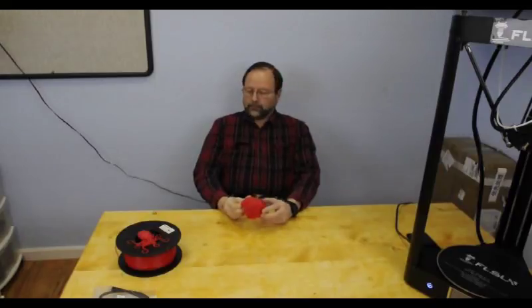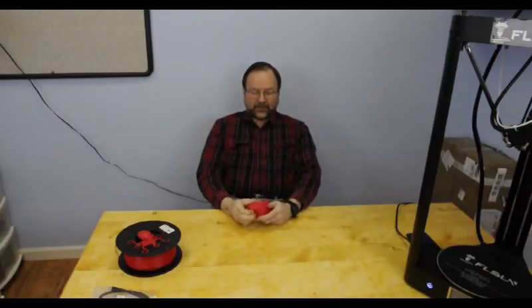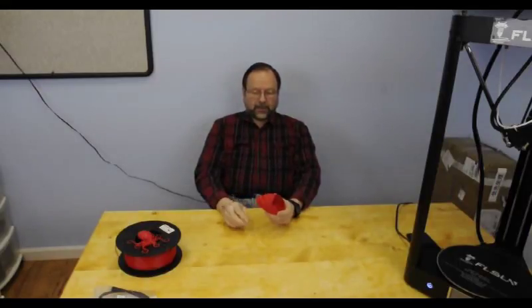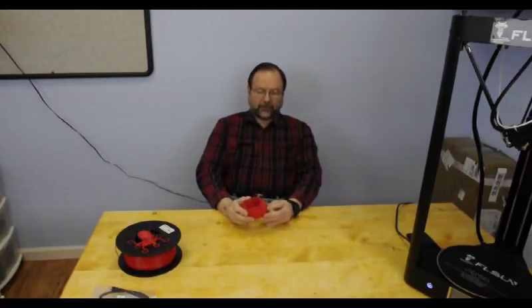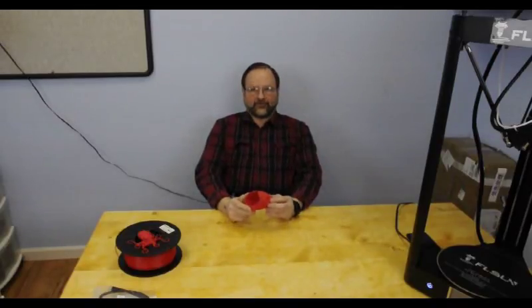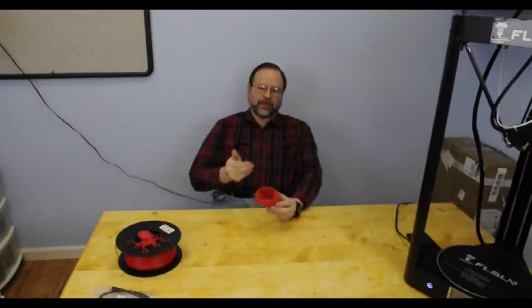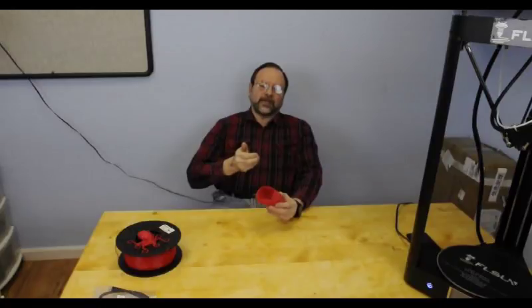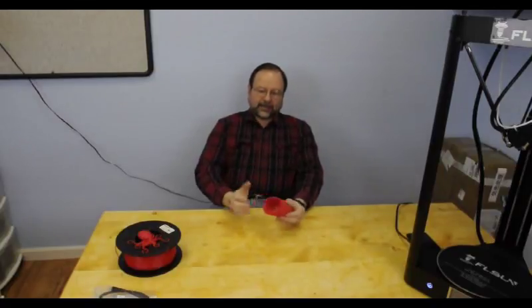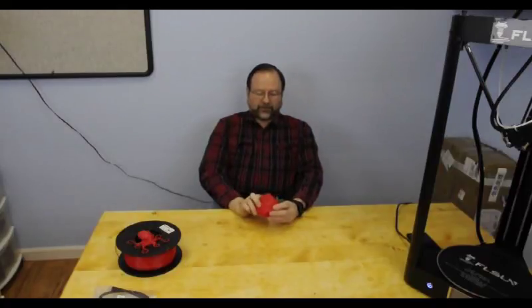Here is the skull printed in Maker Flex. I would say that the QQ handles flexible filaments extremely well. There is some stringing and some little nibs on the model. But part of that is because in order to handle flexible filament without an issue, you really have to turn retraction off. The retraction of the flexible filament doesn't really work because it does stretch. And especially when it's hot, that stretch will suck plastic up into the cool block and cause jams. And also, it doesn't really stop the stringing because since it's stretching, it's not giving any sort of immediate relief to the hot end. So I had to turn those off, which created some stringing.